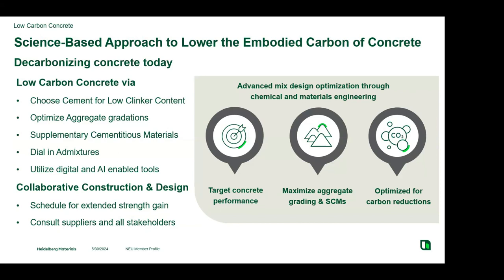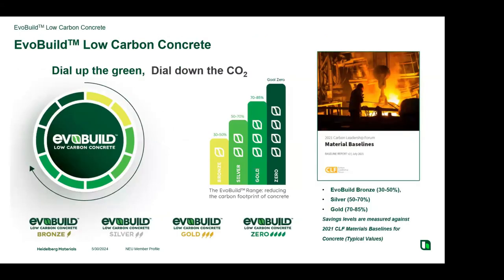So getting back to concrete, in our low carbon concrete, the keys to a successful low carbon concrete mix is to choose the right cements, like we talked about. Utilize a low clinker content in your cement. Make sure that the clinker is made very efficiently. Optimize your aggregate gradations, like we talked about, and dial in your mixes so that they're very efficient. Utilize AI tools, and then of course work together with the project stakeholders. I talked about this a little bit earlier here.